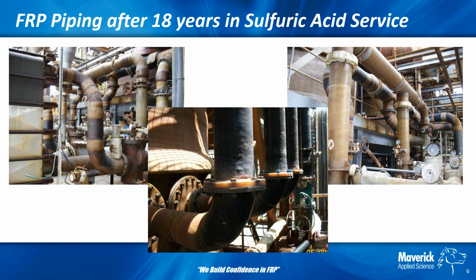When we did this inspection, generally we found that the Barcol hardness readings were approaching upper 40s to 50, which is not really surprising for something of this age. You would expect it to be pretty cured after almost 20 years.